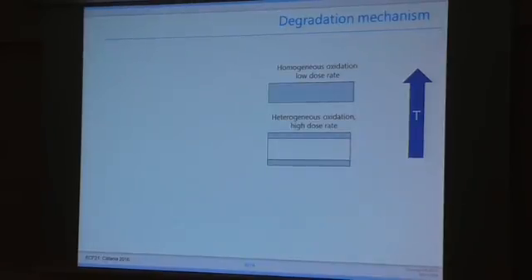So, during the aging process we have oxidation. It can be heterogeneous or homogeneous. Heterogeneous oxidation is very important for high dose rates because we have fast oxidation, which is only strong near the surface of the sample. But if we have a low dose rate, we have more time to reach the same dose, and oxygen has time to diffuse into the sample, so oxidation is more homogeneous. Also, an increase of temperature will enhance the diffusion of oxygen, so it will enhance the homogeneous oxidation.